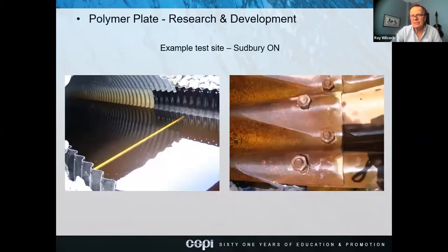We have sites that we wanted to test a number of years ago. This is one up in Sudbury, Ontario, where we had polymer connected to galvanized. This was in very soft water conditions, and we wanted to determine what the impact is, because you do these tests in the lab and they will say that they last 75 to 100 years, but at the same time, you have to do the same tests out in real site conditions. So we have site tests in BC, in Ontario, in Alberta, in Newfoundland, and so forth. And we started these a number of years ago back in the 90s.